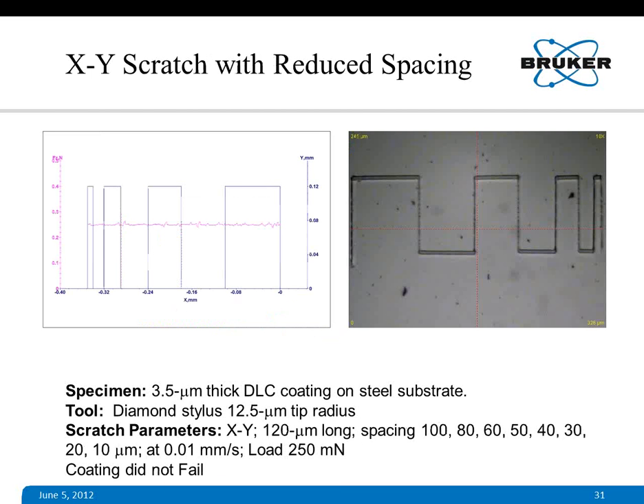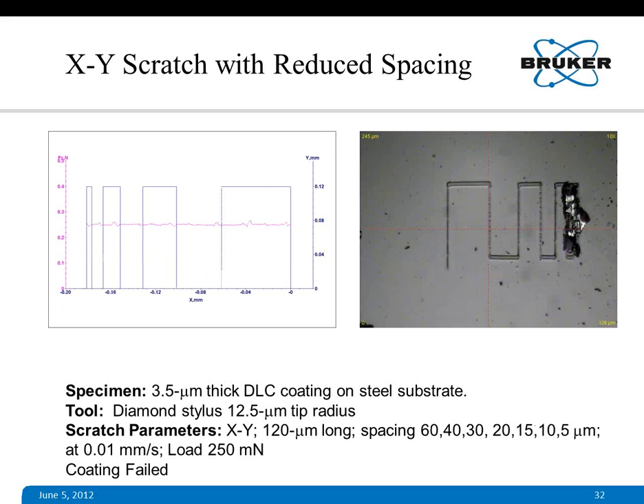We can also perform XY scratch with reduced spacing or different kinds of scratching. This view graph shows that you can scratch with a constant load, but in two different motions continuously without lifting the stylus. And you can reduce the subsequent spacing of the scratch till it leads to failure. In this case, the last spacing was about 10 micron, between these two subsequent scratches along y direction. And it did not fail. The coating did not show any delamination. But when this spacing is reduced to 5 micron, the coating failed.